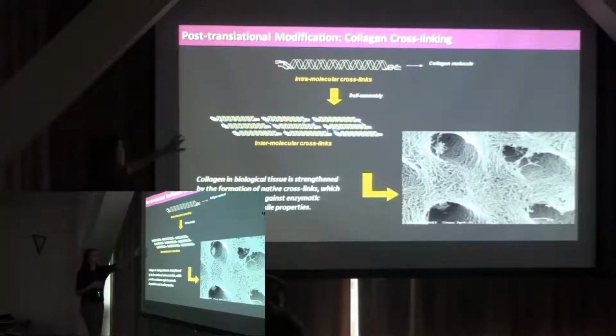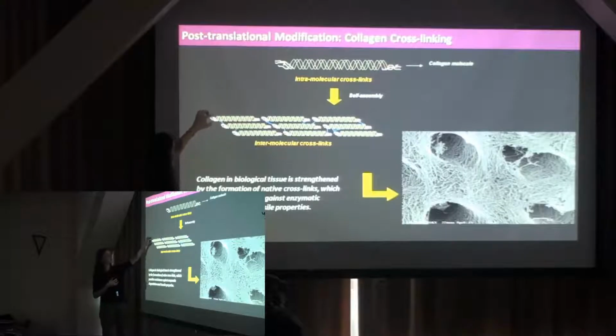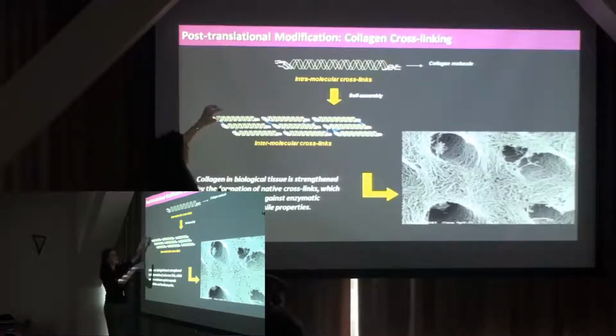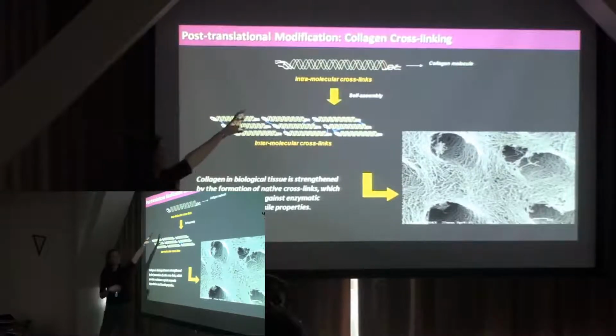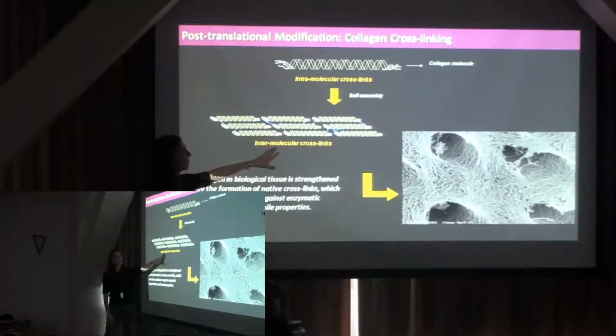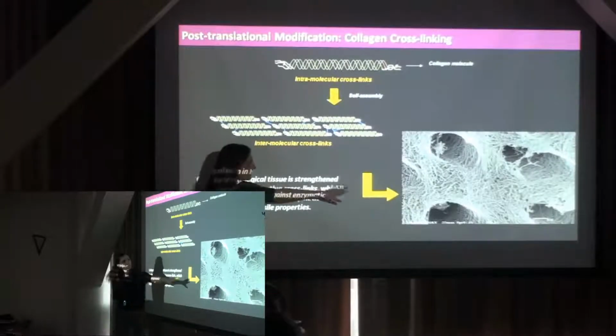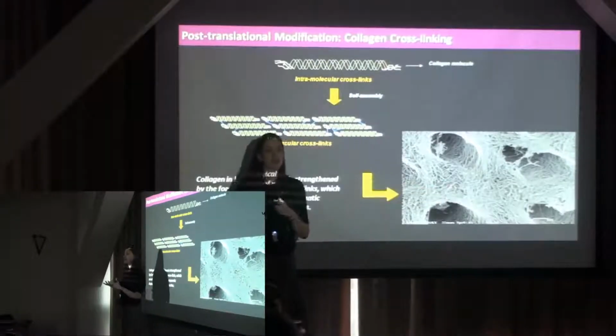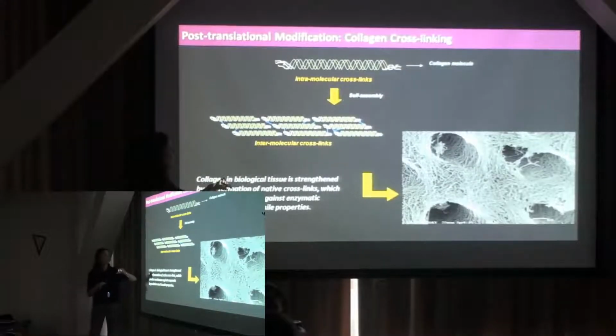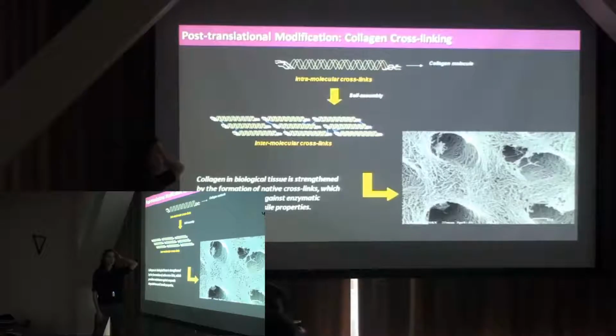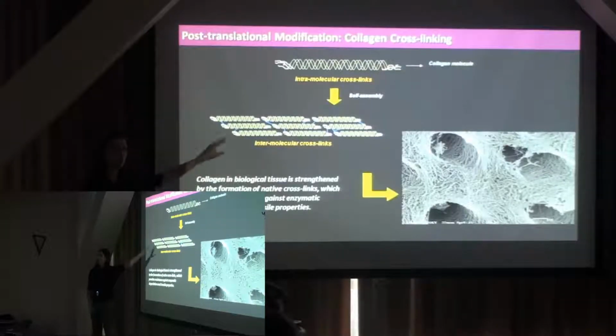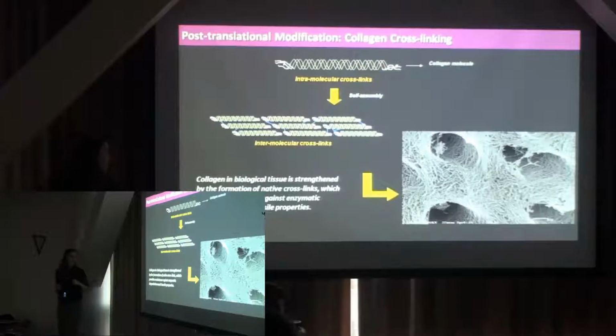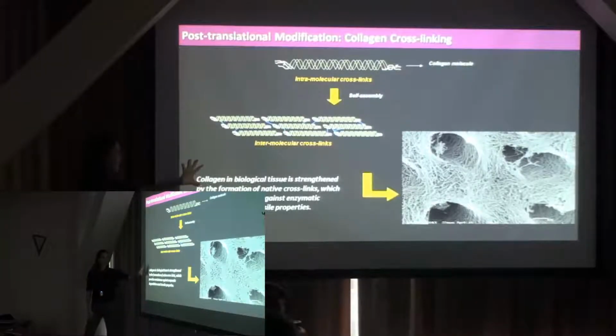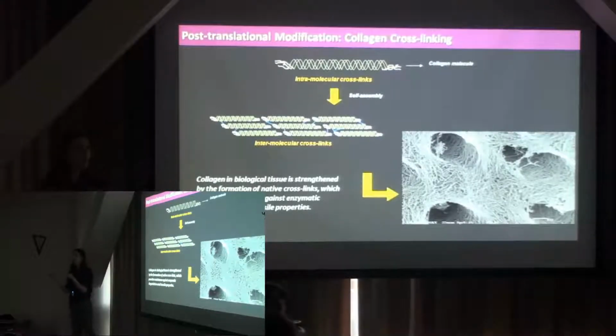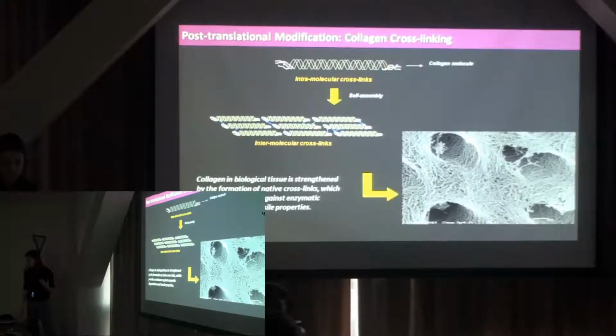During this process, it's stabilized by collagen cross-linking. This collagen cross-linking takes place at the ends of the molecules. So basically, it stabilizes each molecule, but also between the molecules. So we have these intramolecular cross-links and intermolecular cross-links, right? Each one of these is one collagen fibril, all right? Within one collagen fibril, we have about 300 collagen molecules that self-assemble into a fibril. In every tissue, you will have these cross-links, but the degree of cross-linking varies by organ and the function of each organ.